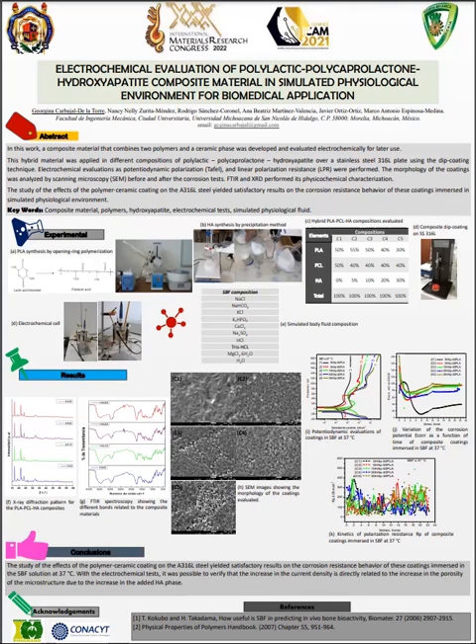In congruence with this, it is identified that the higher the density of porosities and cavities in the coating, the greater the possibility of permeation of the electrolyte towards the metallic substrate, as well as a greater interaction of the medium with the porous microstructure of the composite material. The microstructural characteristic allows greater permeation of the electrolyte towards the metallic surface of the substrate, where oxidation reactions take place, with an increase in the anodic current density, as observed in the shift to the right of the anodic part of the polarization curves.